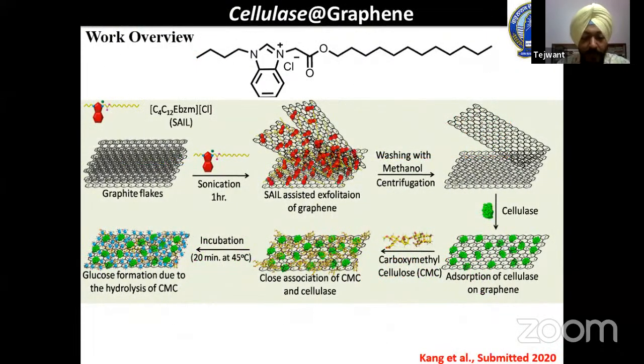So another example, not only the nanoparticles, by using the similar methodology, we have appended the graphene sheets with the cellulase enzyme. So we have prepared some biomimetic systems which can act as the biocatalyst in the presence of enzymes. Here, the benzimidazolium-based surface active ionic liquid, which has been synthesized in my lab, has been used to exfoliate the graphene. And when we add the cellulase, that is the enzyme biocatalyst, that gets appended by surface interactions. That gets adsorbed onto the graphene surface.